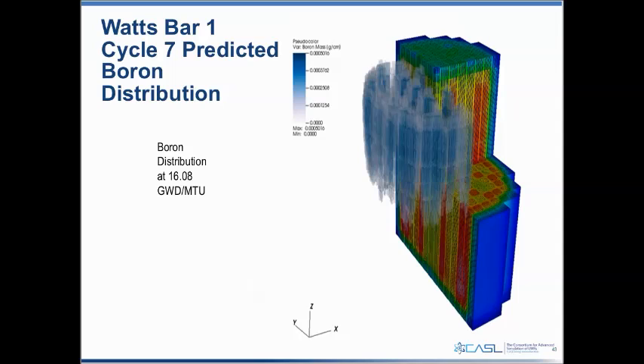Then we also predict the boron deposition at that same time step. You see that gray type material is the predicted boron deposition. So we are able to predict boron in the upper spans, and that corresponds to the thick crud deposits as well. Where you see thick crud, you'll also see the boron deposition.